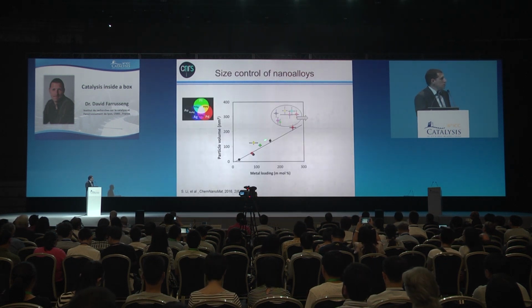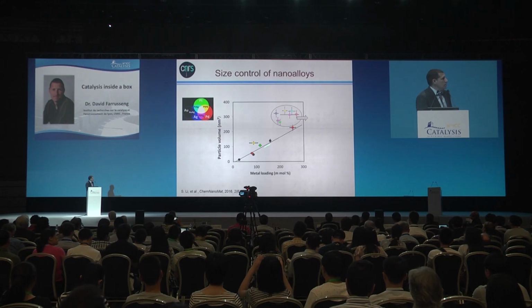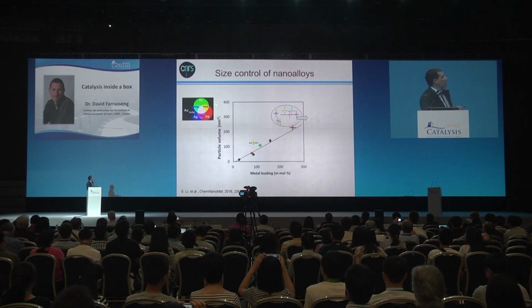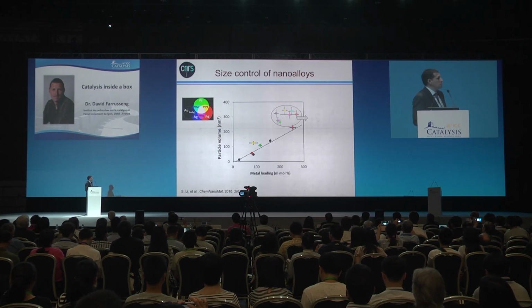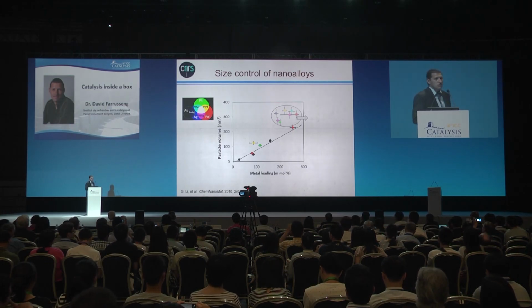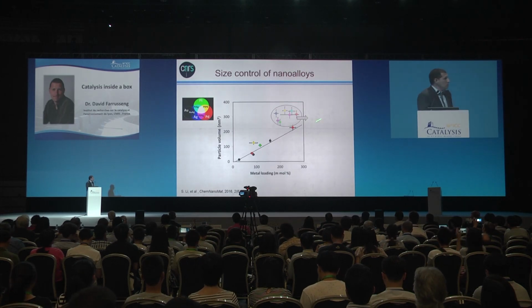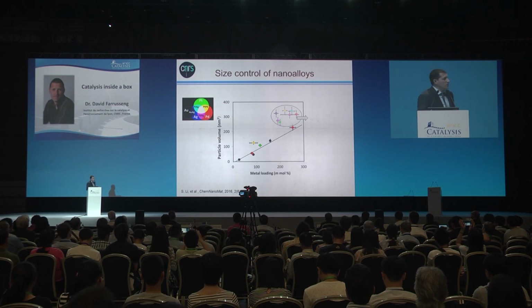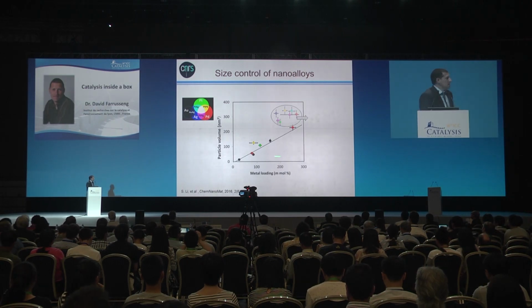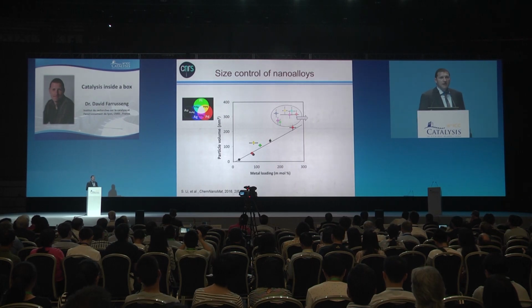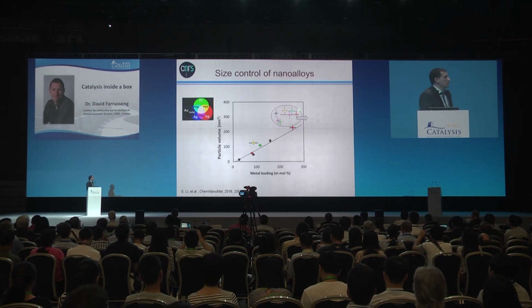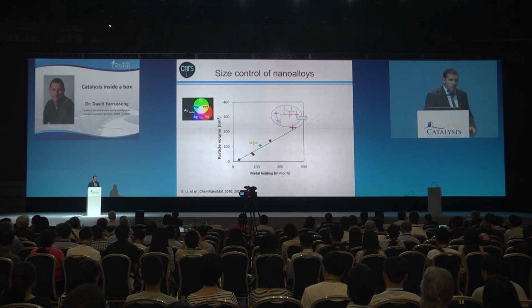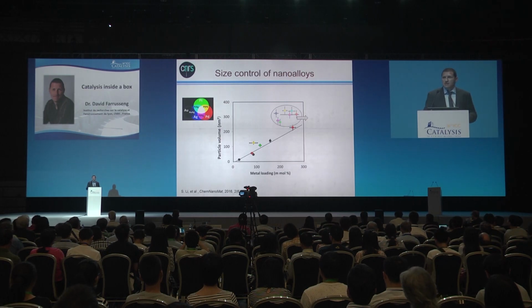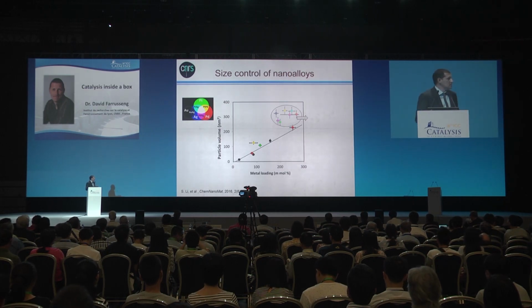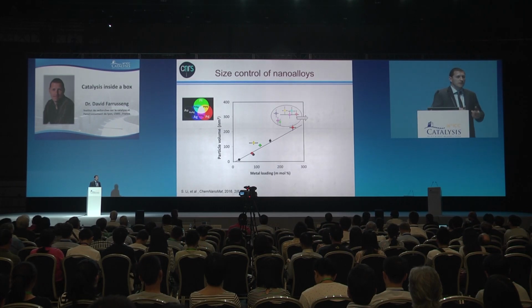We plot also, this is the plot I showed you before, gold and palladium, and we plot them for all these new bimetallic species. What we found is that for high loading, we haven't actually found the same results. And we found later, after a lot of investigations, that the metal loading, which was characterized by ICP, was in fact wrong, because when we dissolved the samples in basic medium, we got precipitate that cannot be solubilized for the